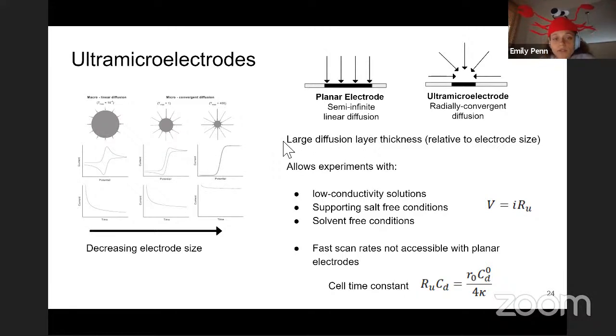The main difference here between the planar electrode and the ultramicroelectrode is the relationship between the thickness of the diffusion layer and the electrode size. So in an ultramicroelectrode, we develop a really thick diffusion layer relative to the electrode size. This allows us to get into a steady state regime where the mass transport is completely controlled by this radially convergent diffusion.